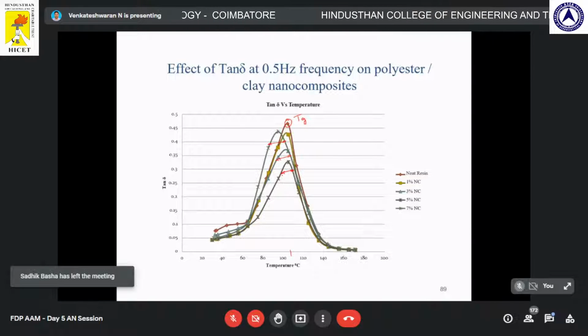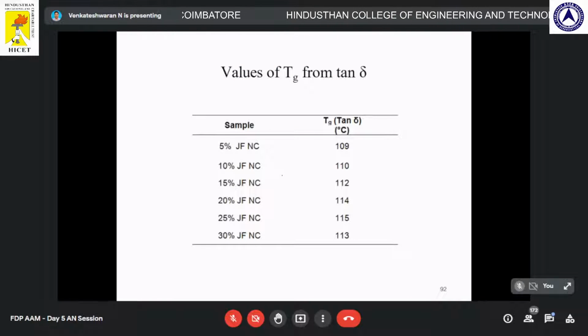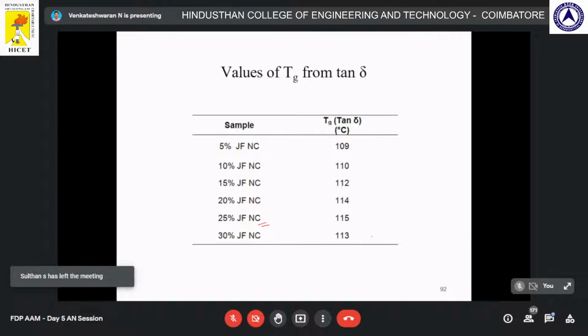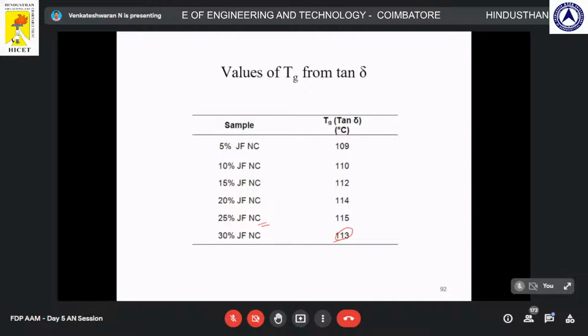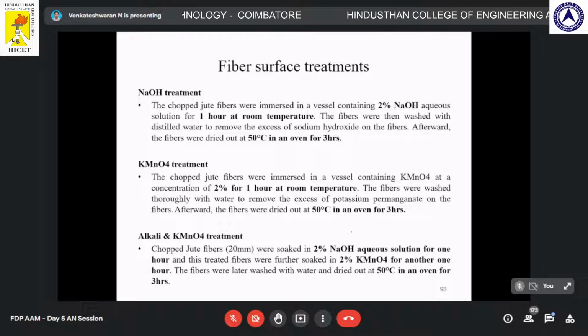So to summarize this, we have a table. The glass transition temperature increases up to 25% of jute, whereas at 30 it starts to decrease. Yes, of course, the difference. If I compare it with the polyester resin, the difference will be very high.